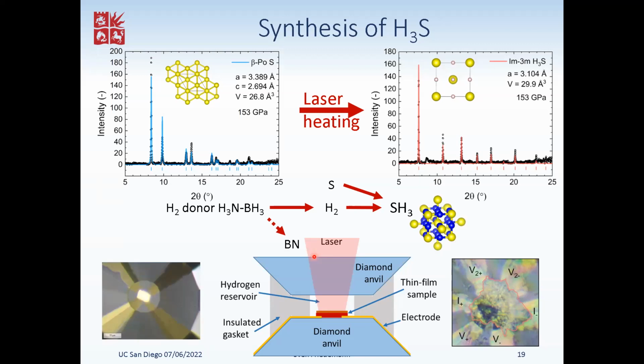That gives you a similar density as if you were to cryogenically load, but both cryogenic loading and high pressure loading have quite serious safety implications, because having a cylinder which takes the whole cell, meaning a volume inside of about a liter, with 2000 bar of hydrogen is quite a safety concern. So not so easy to establish this. I believe there are only two places in the UK that do this, in Edinburgh and at Diamond Light Source.